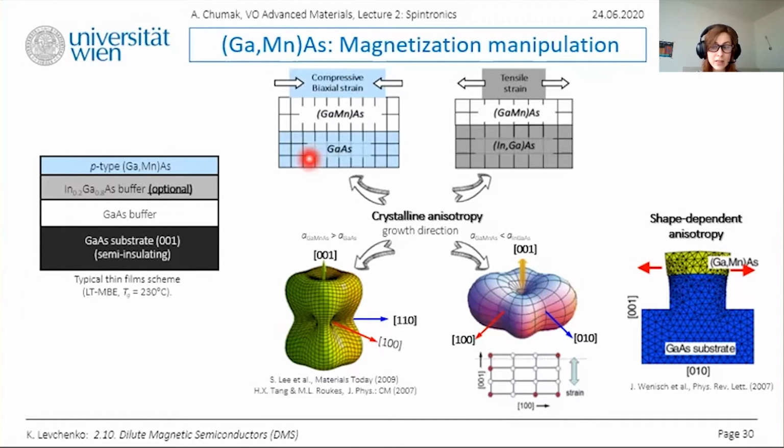We are observing an in-plane magnetization with an easy axis along 100. It's a cubic anisotropy, and an additional contribution arises from non-equal contributions along 110 and minus 110, which is uniaxial anisotropy. As you may see nicely in the picture, it's visualized in the form of the magnetostatic free surface energy, which is derived from magnetotransport measurements under various directions of applied magnetic field at low temperature in helium. The deepest energy minima correspond exactly to the easy magnetization axis.